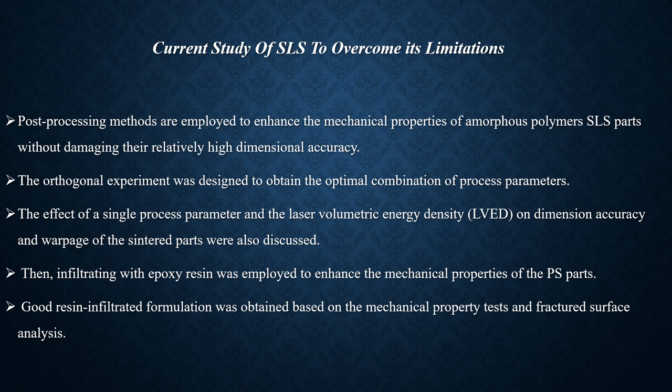Current studies on SLS have found that post-processing methods are employed to enhance the mechanical properties of amorphous polymers SLS parts without damaging their relatively high dimensional accuracy. An orthogonal experiment was designed to obtain the optimal combination of process parameters. The effects of a single process parameter and the laser volumetric energy density (LVED) on dimensional accuracy and warpage of the sintered parts were also discussed. Infiltrating with epoxy resin was employed to enhance mechanical properties of the PS parts.